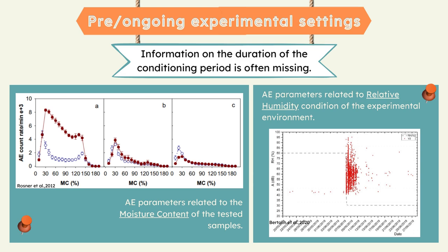80 and 30% respectively. The acoustic emission activity was concentrated over the first days after the hygric change and successively, as the sample equilibrated with the new environmental conditions in the chamber, it decreased.